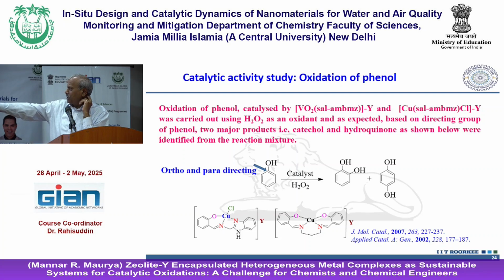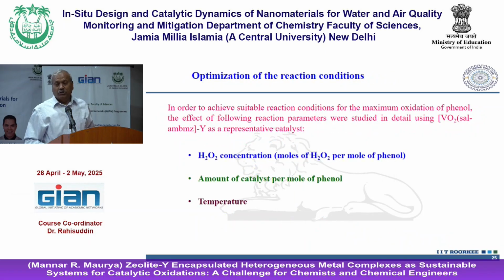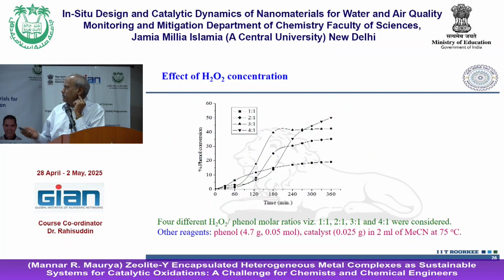This is the salen type of ligand, the second one a copper compound. You see that it should be ethylene diamine, it is propylene diamine. That is the one. Okay, so the first thing was to look at the optimization conditions, because we are using an oxidant. How much oxidant is required to get the best result, how much catalyst is required to give the best result? And if we are doing the reaction in solvent, how much temperature is required. So all optimization was done one by one, and then after the optimized conditions we have these four different plots.